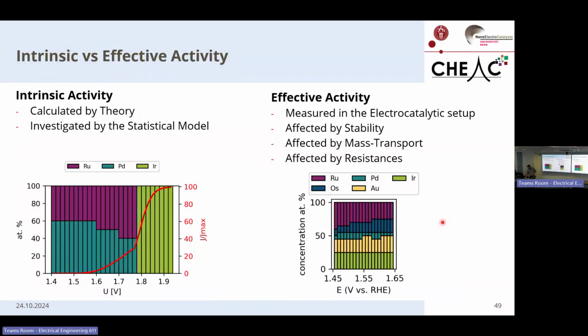And in this case, we believe that while the most active sites are a combination of ruthenium, palladium, and iridium, gold and osmium are necessary to stabilize the system and allow us to measure it in our electrocatalytic setup.